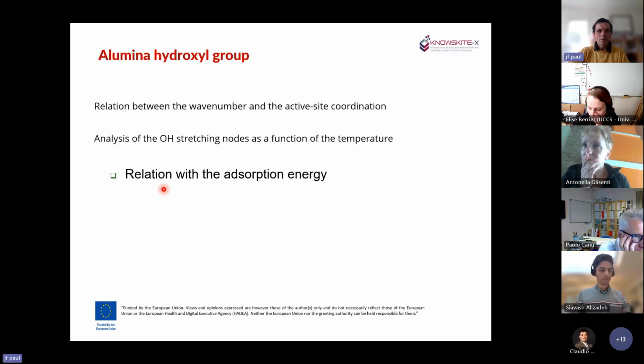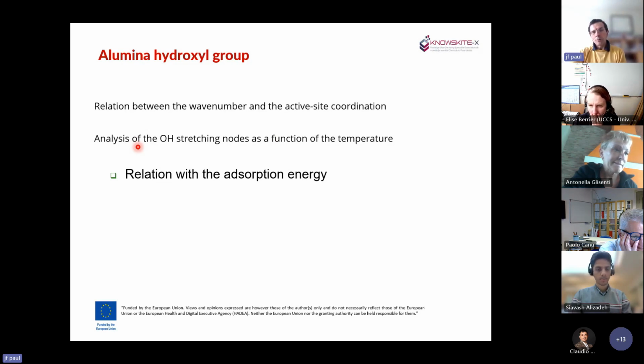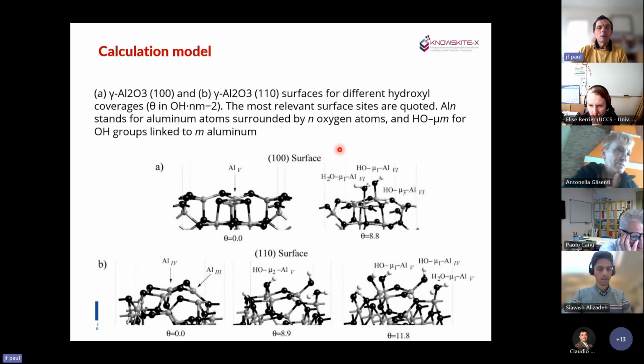Another example, which is quite important, is the alumina, which is a classical support for the catalyst. And one way to characterize this gamma alumina is to consider the OH stretching frequency mode on the surface of the system. And the spectra really depend a lot on the temperature. And I told you before that when we perform the calculation, we did not introduce any temperature in the calculation. So we have to use some trick to add the effect of the temperature.